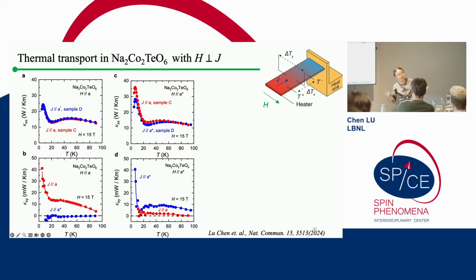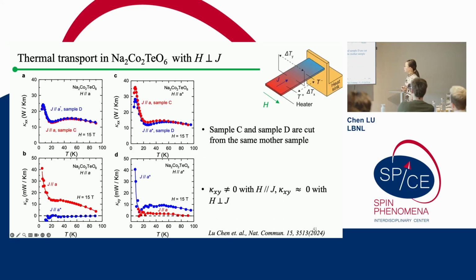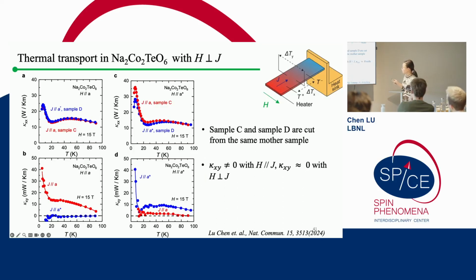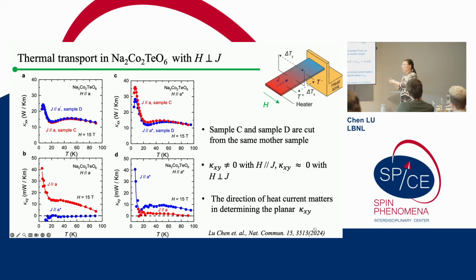Okay, and then we tried to repeat the same thing, but with the field along the A star direction, which is along the other high symmetry direction, and we got something very similar to the other direction. So this tells us that the thermal Hall conductivity is not 0 when the field and the current are parallel to each other. However, it becomes much, much smaller when the field and the current are perpendicular to each other, but in the sample plane. And at this point, it tells us that for the planar thermal Hall effect, the direction of the heat current also matters in determining the magnitude of the so-called planar thermal Hall signal.